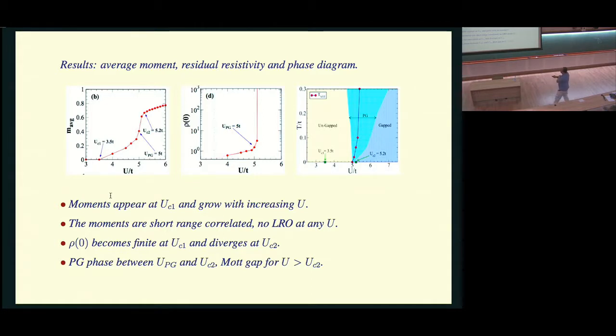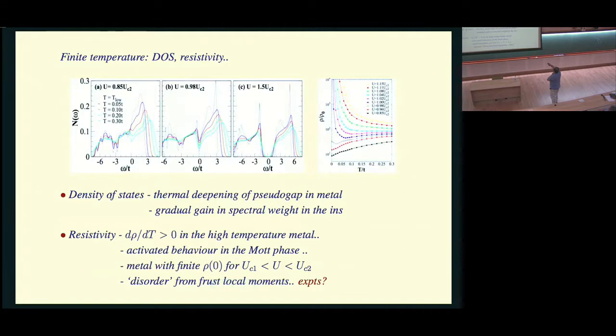In terms of resistance, what one would have expected is that in the metal, because of translation invariance, rho goes to 0 as T goes to 0. In the insulator, rho goes to infinity. There is nothing which should end up at a finite value. A finite value implies something has been broken at T equal to 0. There is a source of elastic scattering, which you don't expect until something very strange happens in an apparently translation invariant model. Now, whether this will survive the quantum fluctuations ignored here is another matter, which I'll come to at the very end of the story.